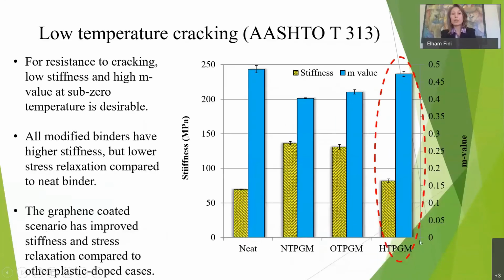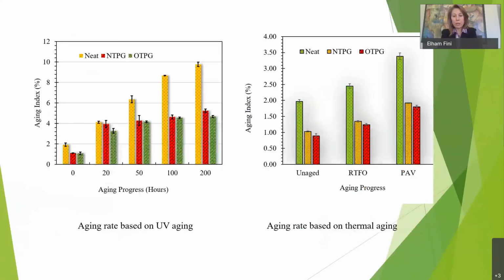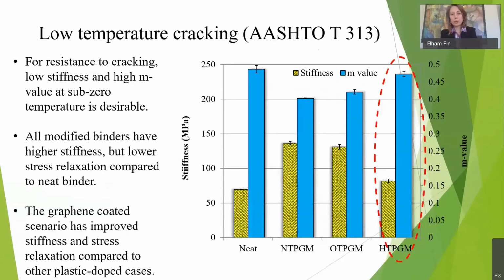And again, here, for the low temperature, relative to other samples, the hybrid treatment did pretty well. Here, the graphene coating, the hybrid coating, helped big time with the stress relaxation, which was really impressive. You can see compared to these other two samples, you have higher stress relaxation, meaning it doesn't accumulate the stress to cause cracking. So with this series of tests, we actually got the performance characteristics. It seems it meets the criteria that we typically use.